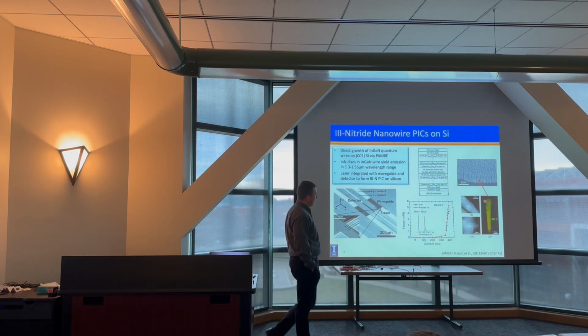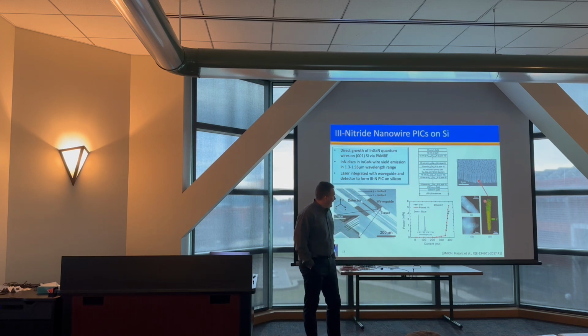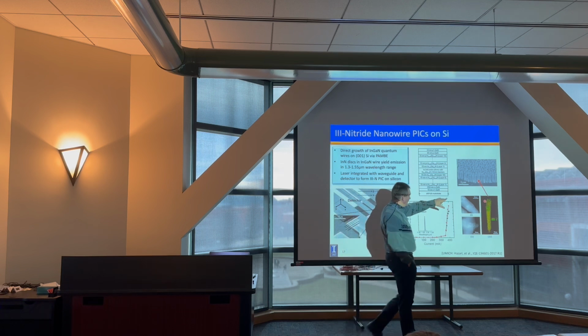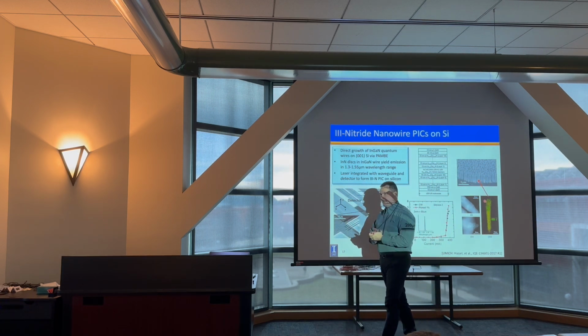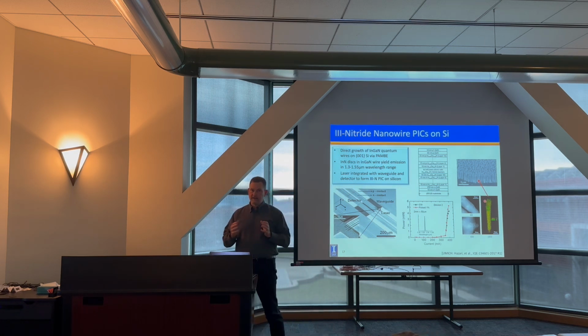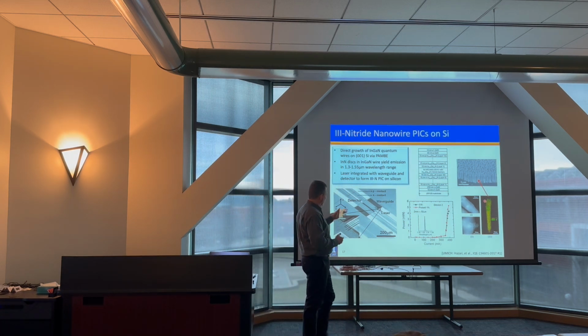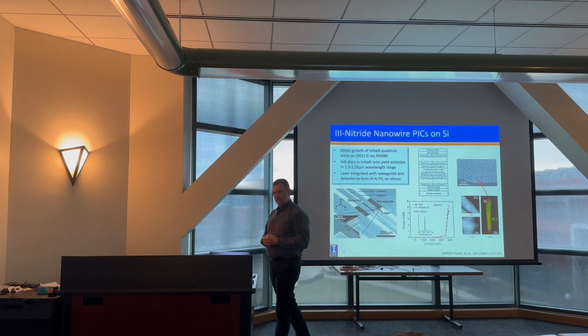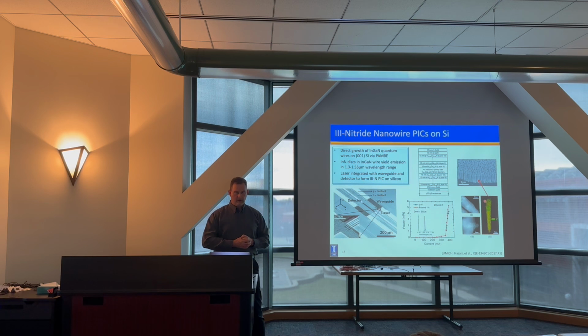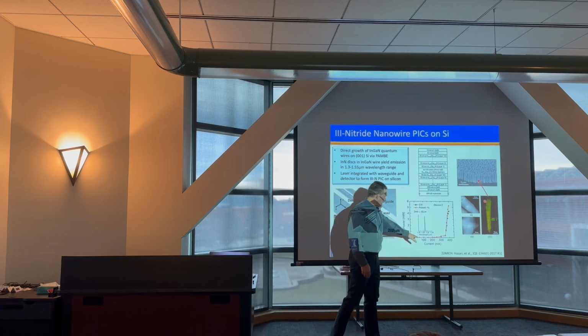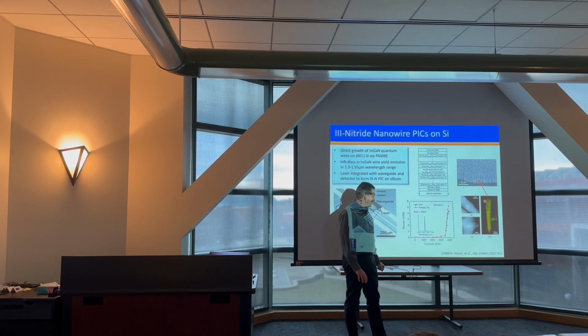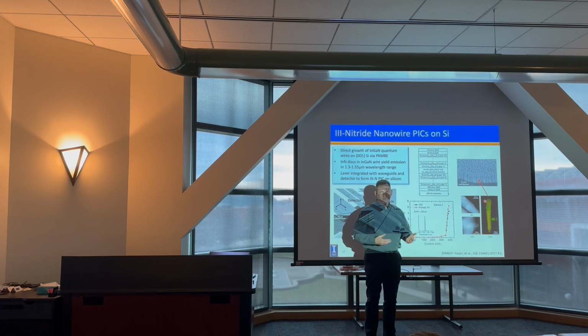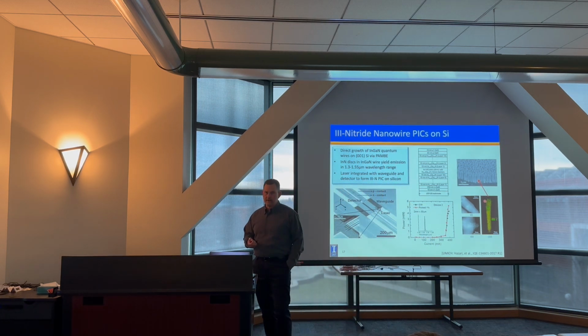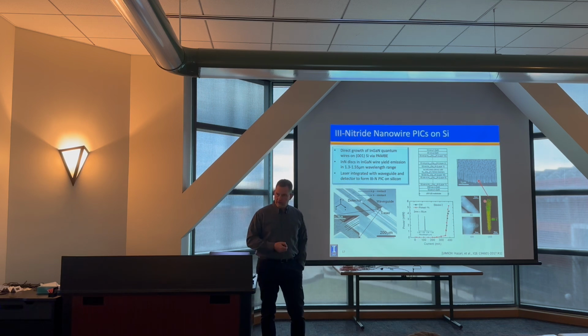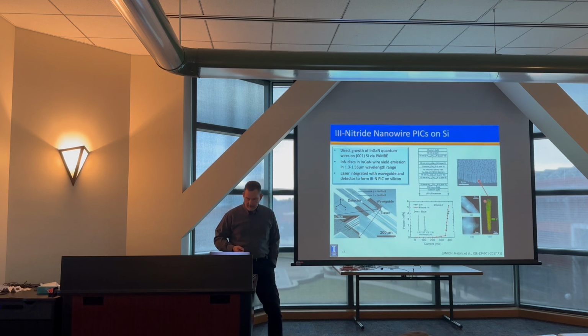This is some other interesting work. This came actually out of the University of Michigan. Here what they were doing was growing nanowires of gallium nitride, basically III-nitride devices on silicon, and making lasers, detectors, and waveguides using this nanowire material. Now, these devices weren't great. Well, I'm not going to say lousy, but the threshold currents were high. There were various problems with them, but it basically showed promise as a technique for integrating those materials onto silicon, again in a wafer scale process.